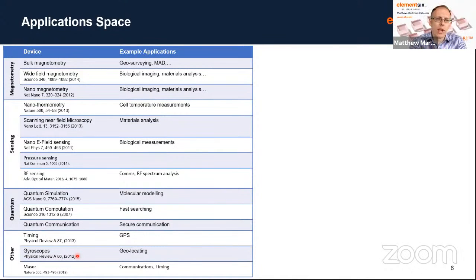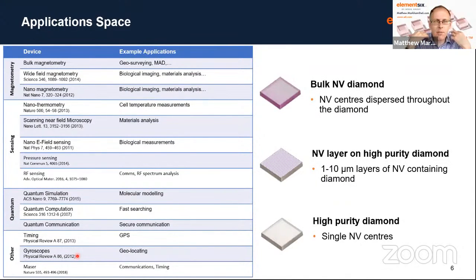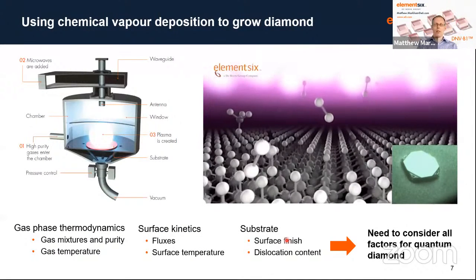From a diamond perspective, what's actually quite good is that the materials required for these applications, you can basically split them into three different camps. It's basically bulk materials where you have uniform NVs throughout the material, NV layered material where you have thin layers of NV enriched material on top of what is otherwise low NV material, and material which is high purity diamond where you can use single NV defects. So I'll go through how we make those materials.